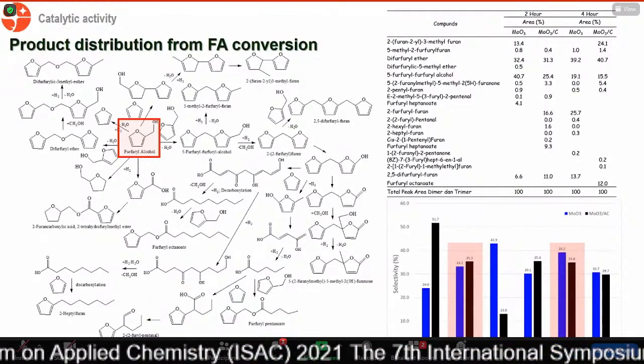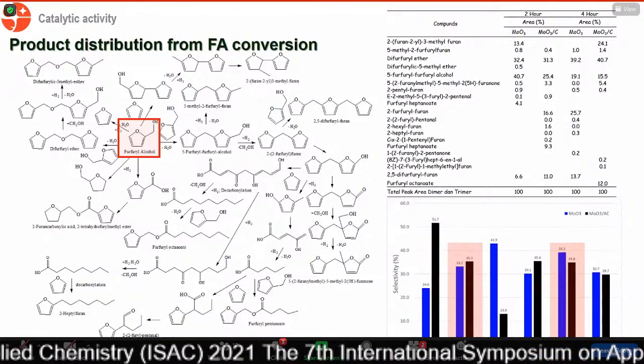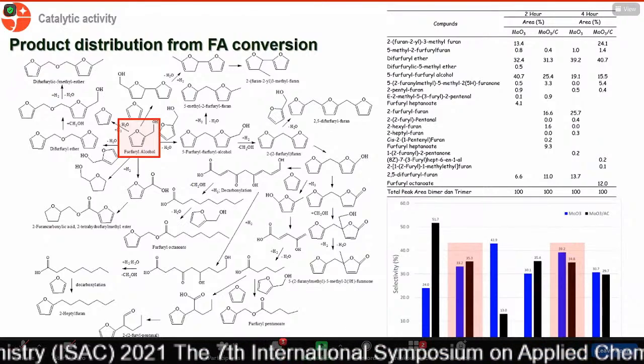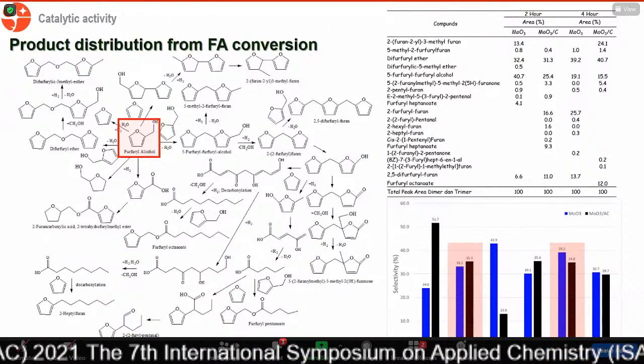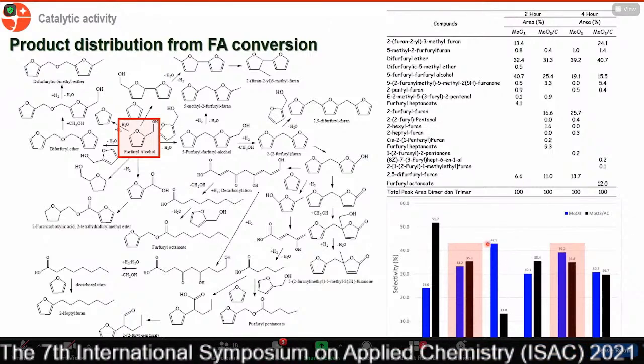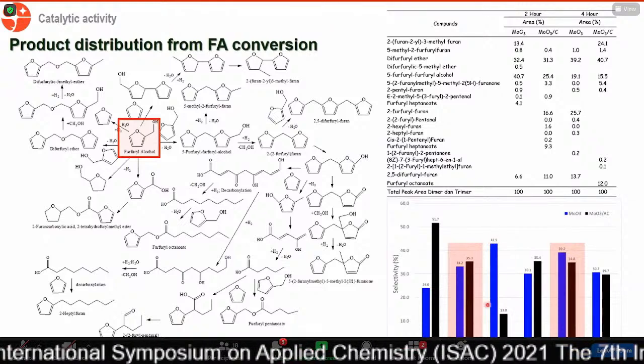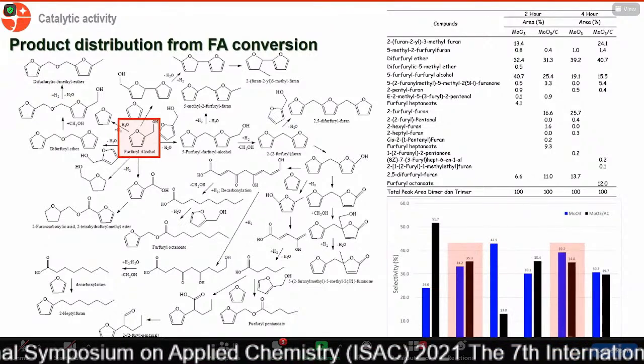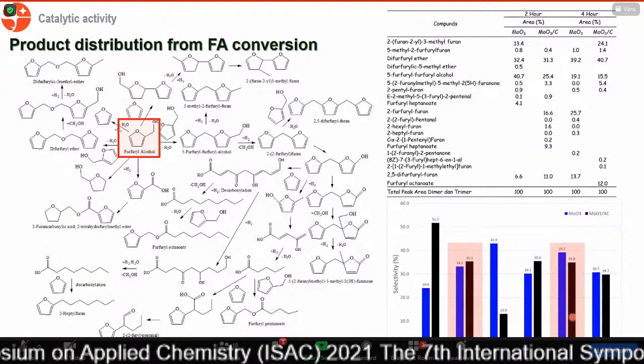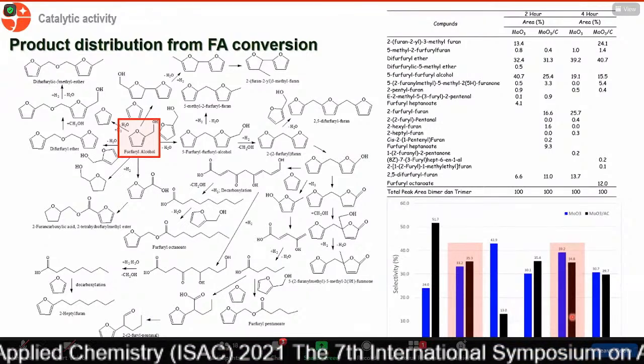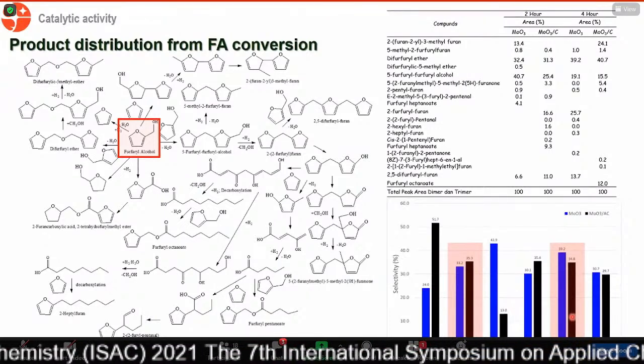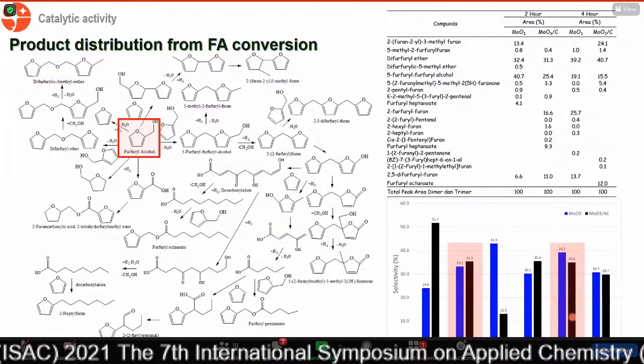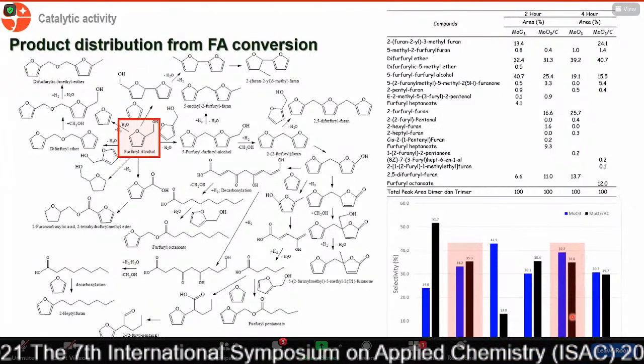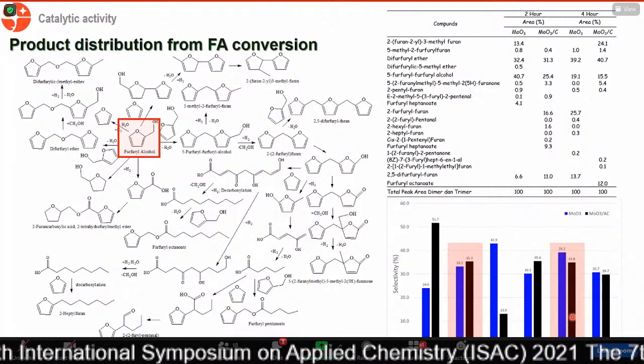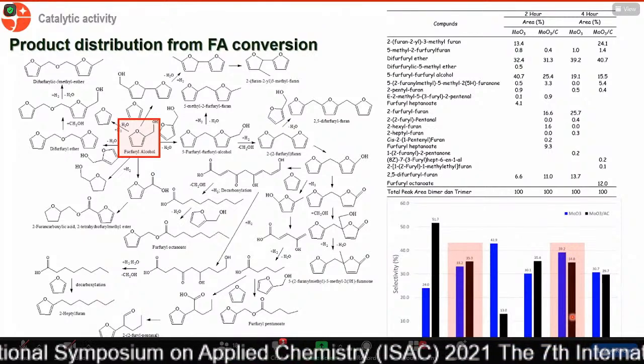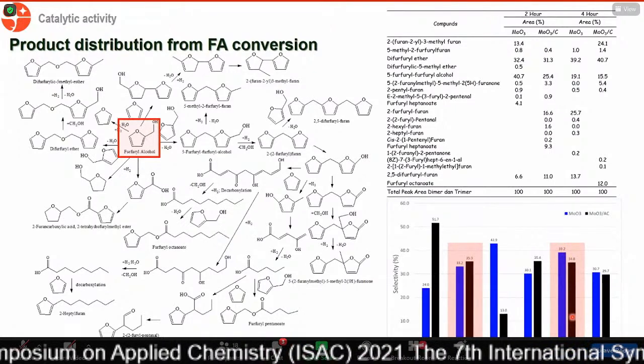And the last one, the group which contains unknown compounds that we could not assign from our MS result. And from this result, we can see here that at 2-hour and 4-hour reaction, the product distribution for dimer and trimer compounds for both catalysts is quite similar, which means that there is no effect on the selectivity of the catalyst after loading on the activated carbon.